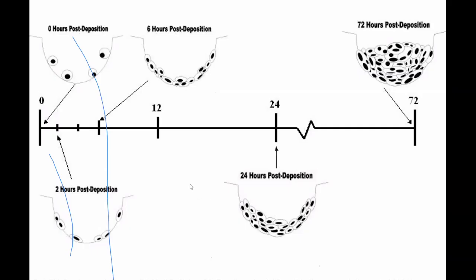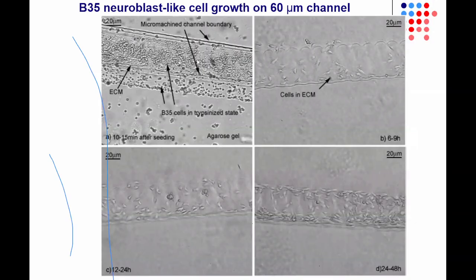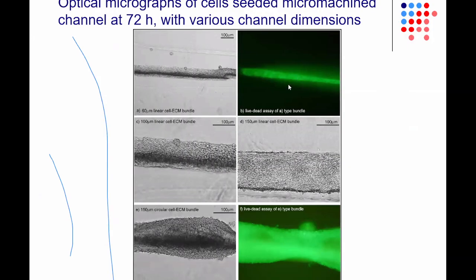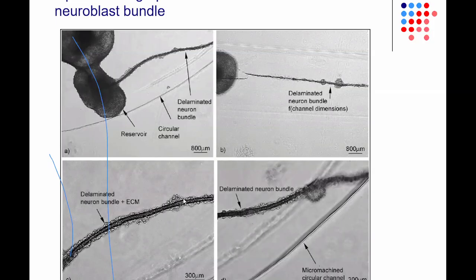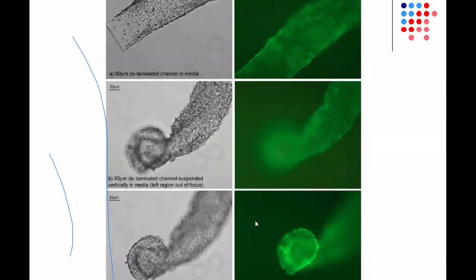And so eventually you can get these structures that are cell-seeded channels. This is an interesting example where you have B35 neuroblast-like cells that will align within these channels. Eventually these bundles will break free from the channels. They'll have enough cell quantity that they'll detach from the channels they were originally in. Then you have these delaminated neuron bundles that will come off from the micromachined channels. And you can see here examples of these delaminated channels.